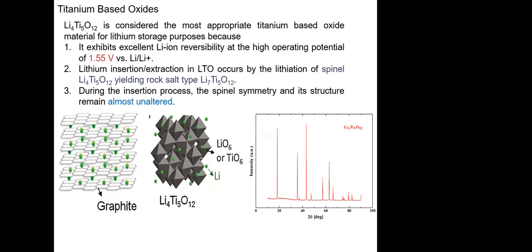Okay, so this LTO is the material recommended for public transportation like buses. The disadvantage is that when you incorporate lithium titanate with the NMC or LFP, your energy density goes down, because this material has nearly 1.5 volt potential. So the cell voltage comes to nearly 2.2, 2.3 volt. So the energy density in this, you get only 85 to 90 watt hour per kg. Okay, but it has the advantage, one of the safest,